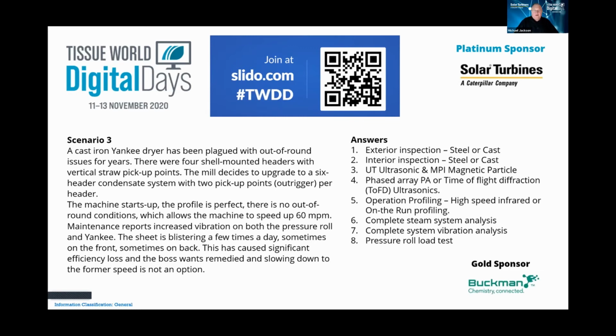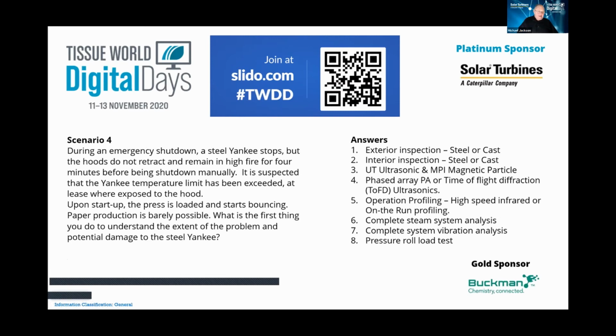Right, we're going to close voting on that in just a second, and I'm going to ask Agnes to show us scenario 4. We have 2 more to go, ladies and gentlemen, and this is the second last of these. Number 4, during an emergency shutdown, a steel Yankee stops, but the hoods don't retract, and they remain in high fire for about 4 minutes before finally being shut down manually. It's suspected that the temperature limit on the Yankee has been exceeded, at least where it's exposed to the hood, and upon startup, the press is loaded but starts bouncing. Paper production is barely possible.